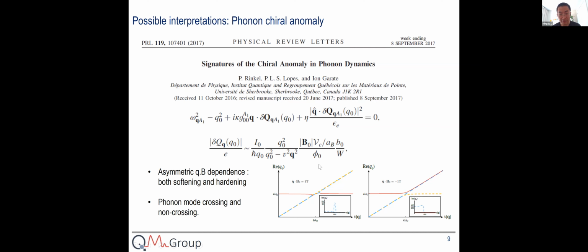Chiral anomaly just means this fundamental CP symmetry breaking. In this particular case, when you have some kind of phonon and an external magnetic field aligned with each other, it had been predicted almost 6 years ago by the theory group in Sherbrooke that this kind of asymmetric phonon change would occur. Imagine you have some kind of optical phonon, and if you have the positive polarity, it may hybridize with the so-called pseudo-scalar boson mode, and it really doesn't change too much. But if you switch the polarity, then the gap opens.